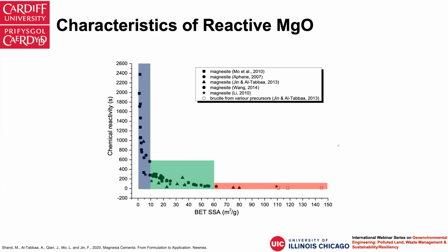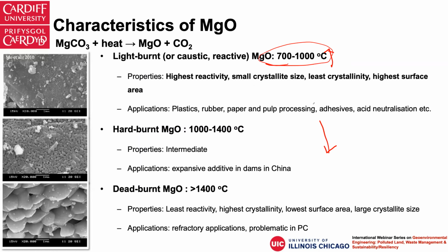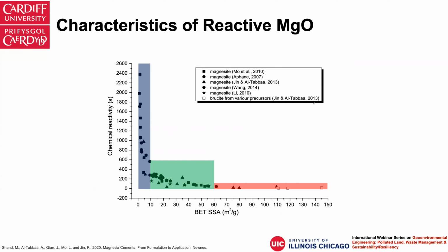And even within the reactive grade of magnesia, those calcined at lower temperatures, the characteristics and reactivities vary vastly as well. One of my tasks in my PhD is to categorize these reactive grade magnesias based on different indicators. This figure shows an arbitrary categorization of reactive grade magnesia based on surface area as well as chemical reactivity. I've categorized them into three groups: low reactivity, medium reactivity, and high reactivity. These are purely arbitrary, but it gives us a rough guidance of which ones we are using. And the reaction rate with different phases really depends on which phase you are going to react magnesia with.